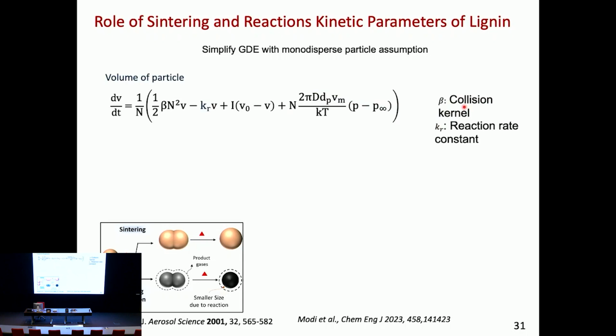Now, I can definitely not use a spherical assumption now. So I track the volume of the particle, which is the size of the particle. And just to point out, the first term increases the size or the volume by collisions. When two particles collide, the size will increase. When I have chemical decomposition, it's going to reduce the size. If I have some nucleation due to vapors, depending on the critical size, again, I'll tend to increase the size. And the last term is that condensational growth term. So we really account for all of this.